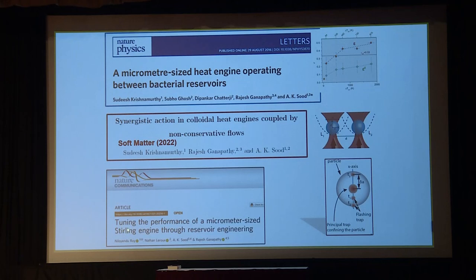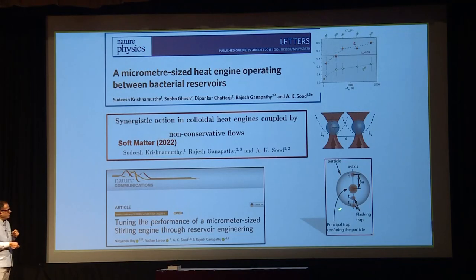And more recently, in Professor Rajesh Ganapathy's lab, Nirlendu and others have a very, very unique system to vary the effective temperature. No bacteria, nothing. What you do, in addition to the laser which is trapping this colloidal particle, is have another laser which fluctuates randomly around this axis. So this creates noise. And what we have shown is it can give you an effective temperature as high as 2000 Kelvin. But the water temperature with a thermometer is still 300 Kelvin.